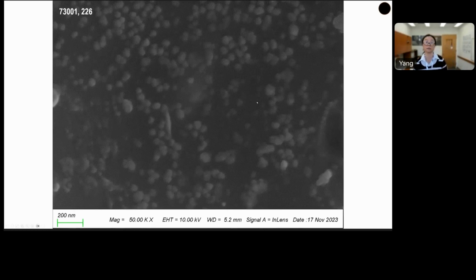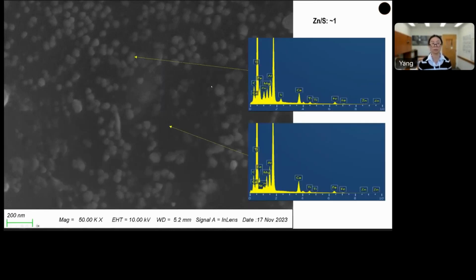Now we're at 50,000 times magnification. You see those little subangular grains. Those are zinc sulfide grains. So we can compare the chemistry. Sorry about the fuzzy images. With the EDS spectrum, we can compare the area with and without these little grains. And as you can see, we detect enhanced zinc and sulfur content when we compare those two different regions.